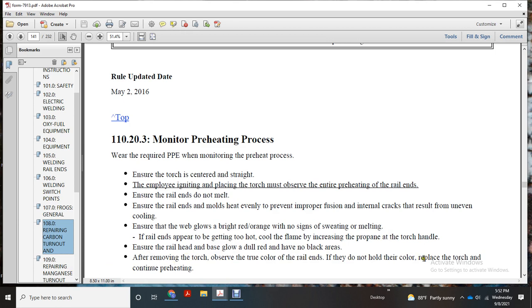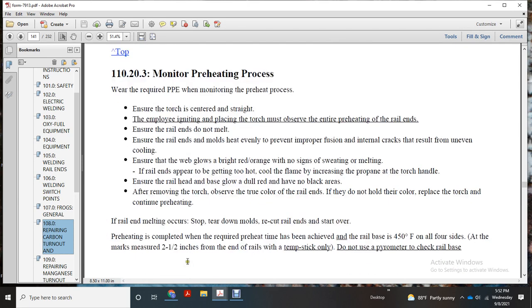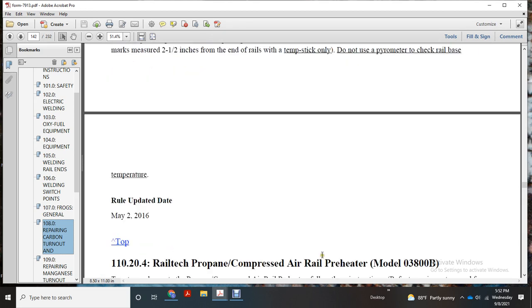If they do not hold the correct color, replace the torch and continue preheating. If rail end melting occurs, stop, tear down the molds, recut the rail ends and start over. The preheating is complete when the required preheat time is achieved and the rail base is 450 degrees on all four sides. This is measured at 2.5 inches from the end of the rail with a temp stick only.